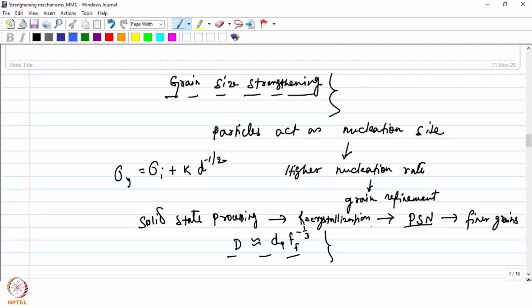Then we talked about the grain size strengthening, which comes into play in metal matrix composites also. This is due to the fact that the particles act as nucleation sites, and that will increase the nucleation rate and give rise to grain refinement. And this can even happen in solid state processing when recrystallization occurs. So particles of a given size can stimulate the nucleation in the recrystallization process, and this particular phenomenon is known as particle stimulated nucleation, and therefore in the recrystallized material the grains will be finer, and therefore the strengthening effect will come from the grain refinement strengthening as per the Hall-Petch relationship.